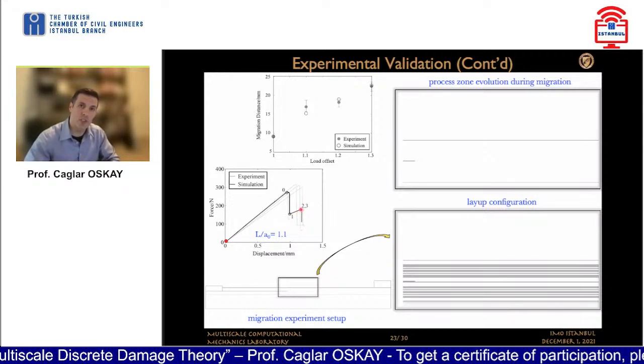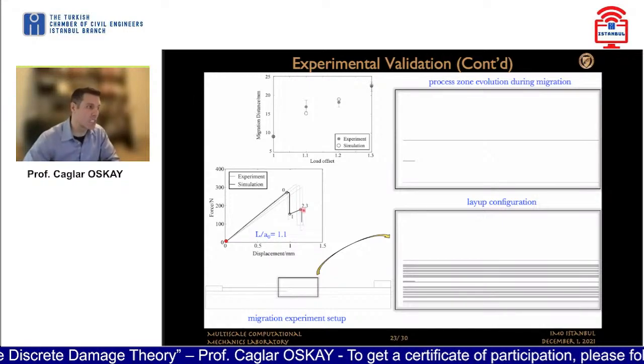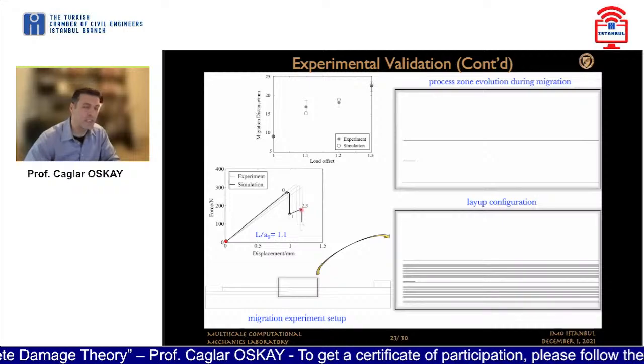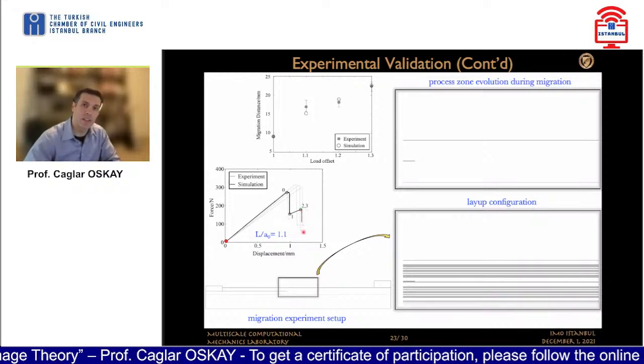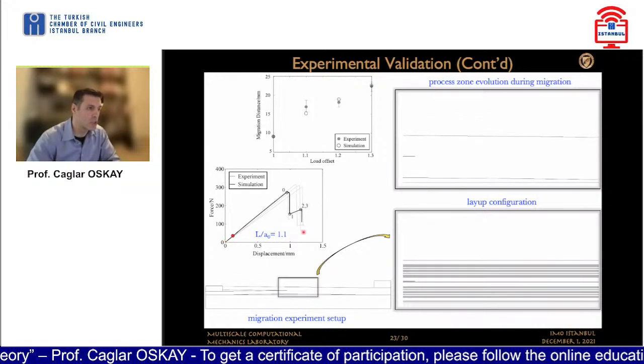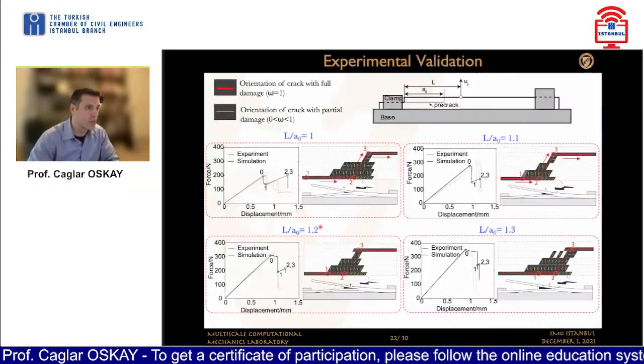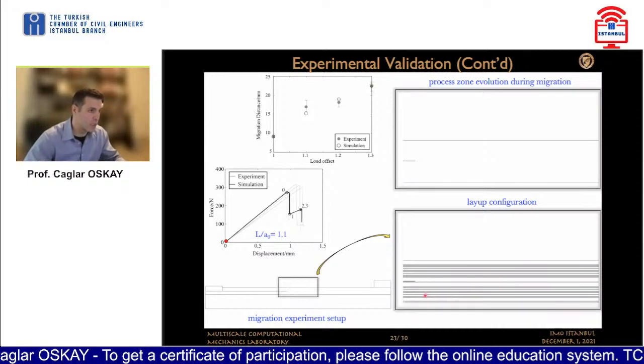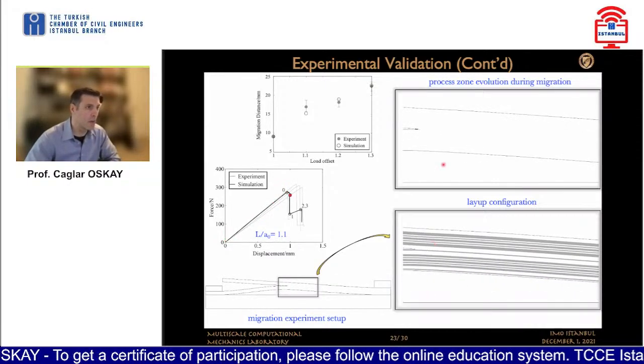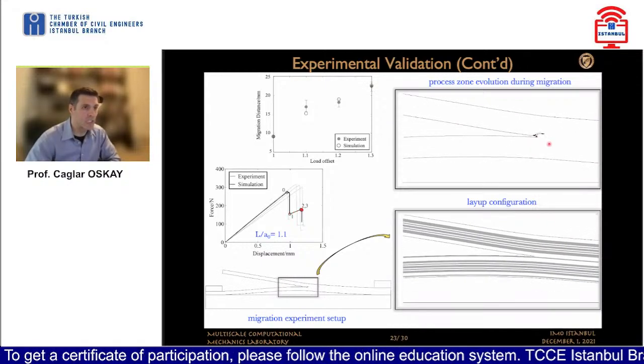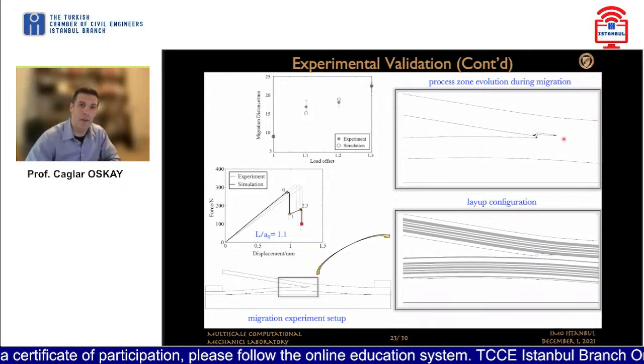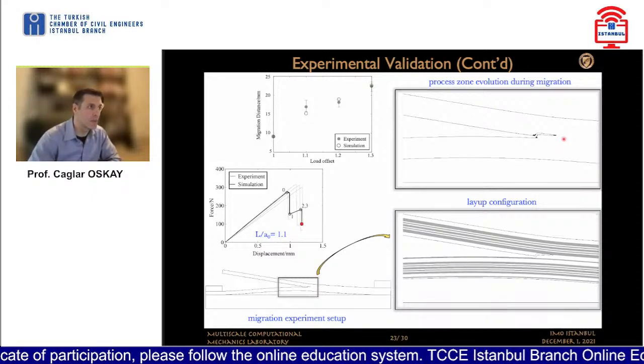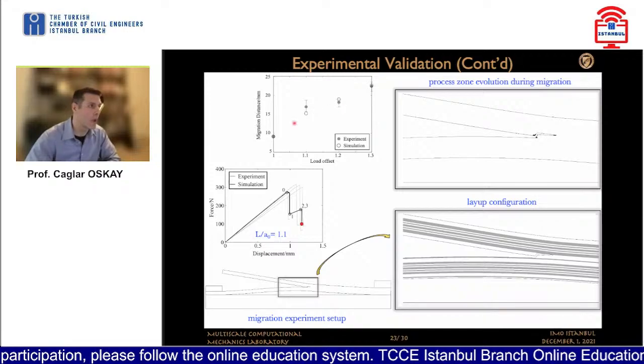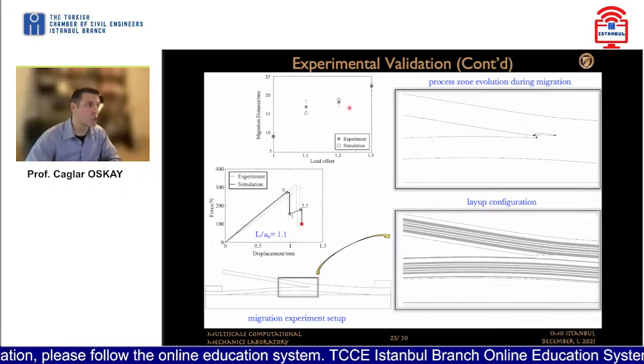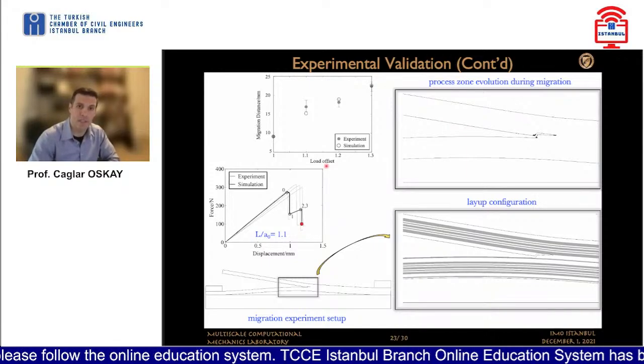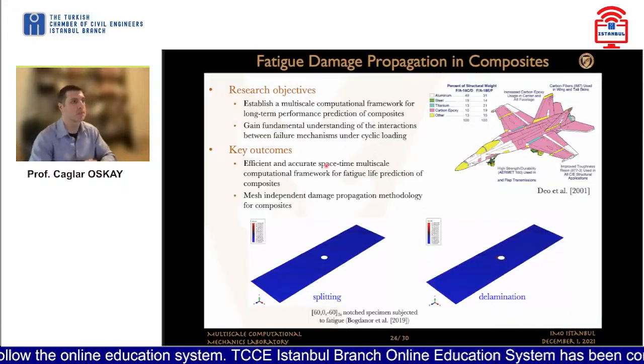By the time you get to 2, the delamination process starts and ends quite quickly. Finally, the second drop is associated with the delamination migration again. And let us look at the last figure. I'm sorry, it's not working again, but let's see. Yeah, it's working now. You see the crack starts to propagate, stops, and migrates and cracks again. So we have been able to capture this pretty accurately, and the evolution of the migration distance as a function of load offset is very much in line with the experimental observations.